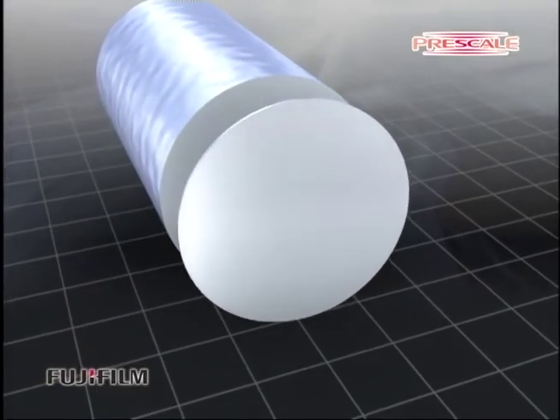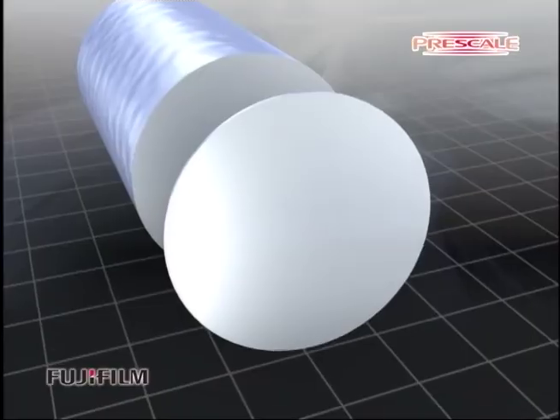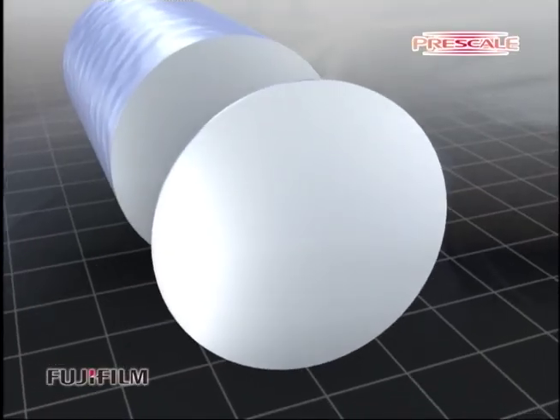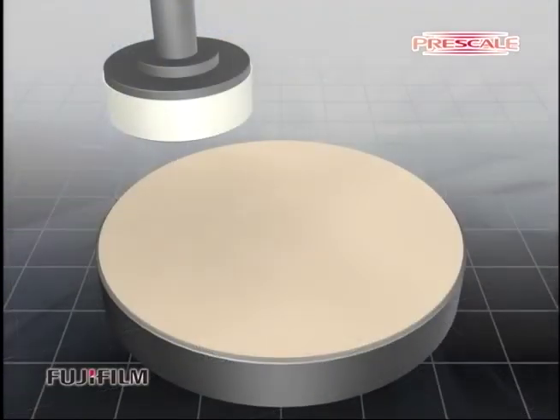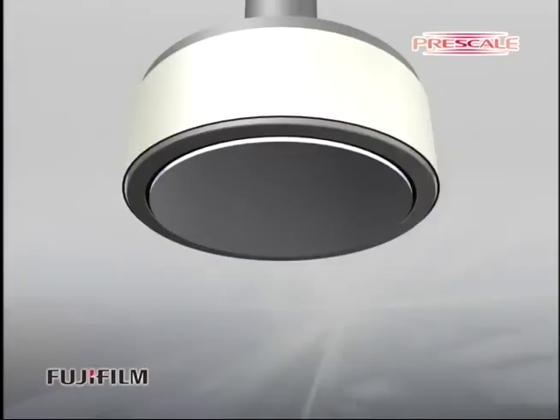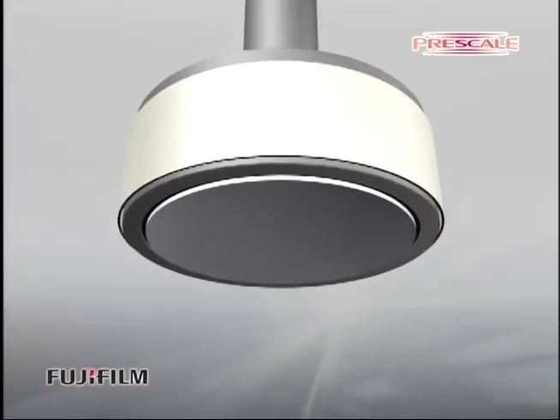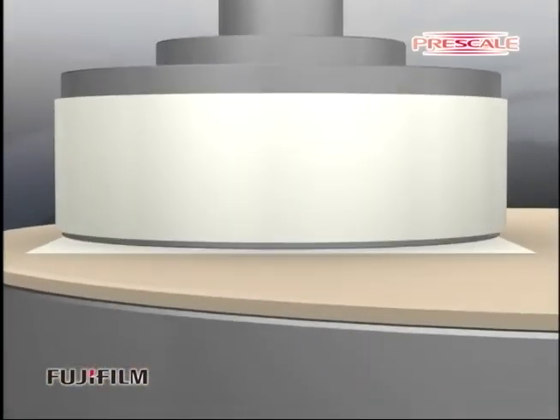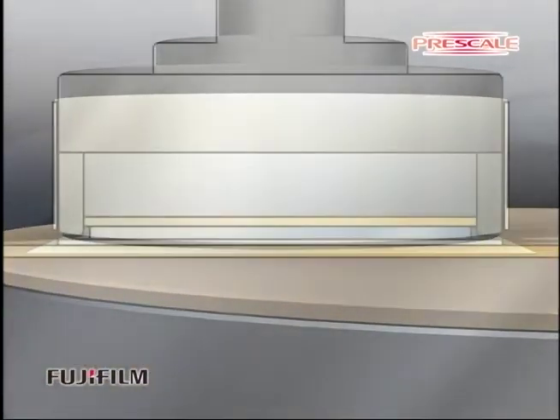The next application is a measurement of a silicon wafer surface polishing pressure. Place a Prescale that is slightly bigger than the wafer on the rotating level block. Place a polishing head with a mirror finish surface wafer on the block and keep pressing it with an even force for a few seconds.